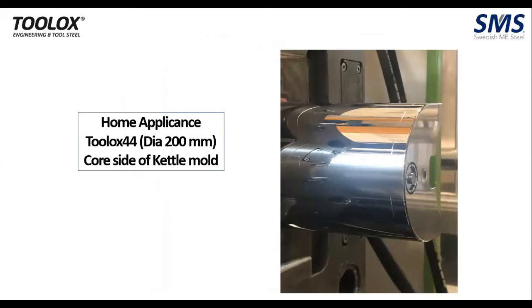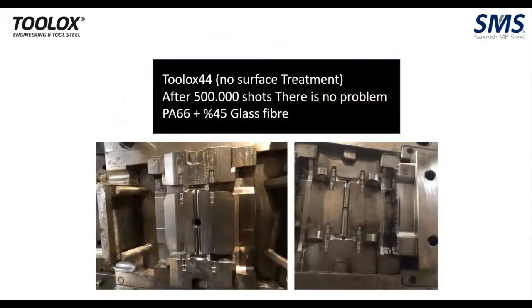Home appliances: Toolox 44, dia 200 mm, core side of the kettle mold being made. Again, for one more plastic with 45% glass fill. As you can see from two different pictures, one before using and one after completing 5 lakh shots, Toolox 44 without any surface treatment at 45 HRC after 5 lakh shots, you can see that it is relatively new.